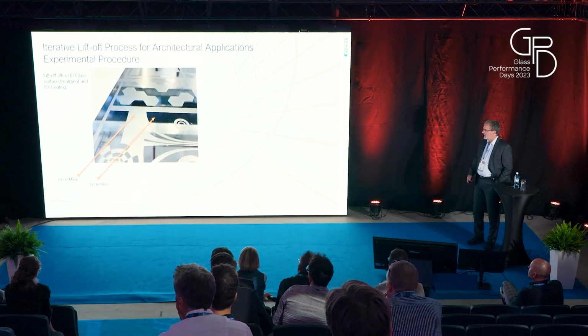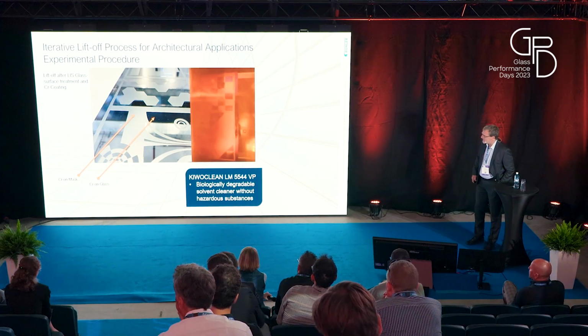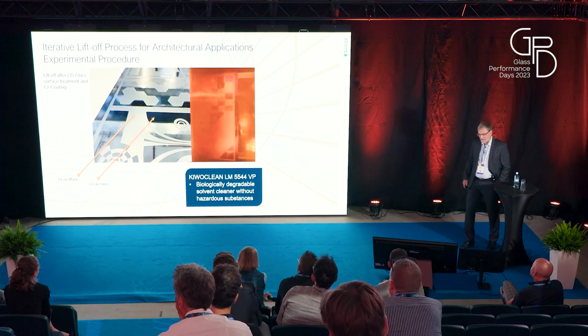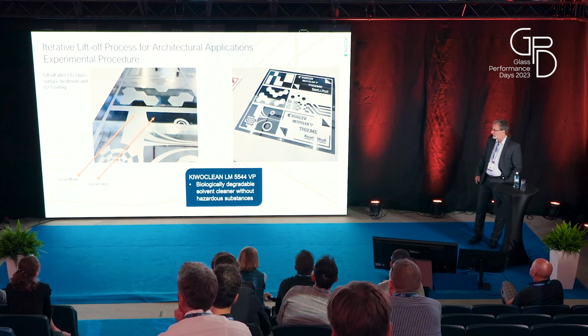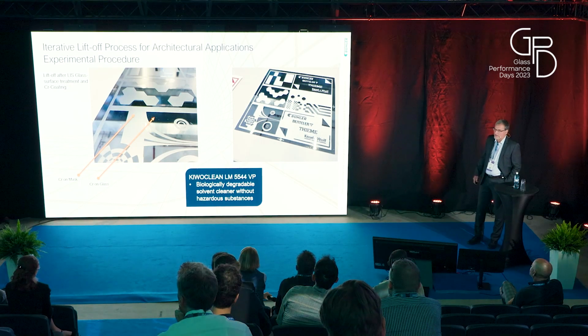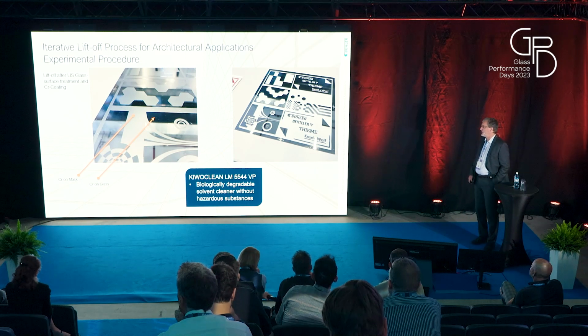So we did this again. So it was the coating, and then again, in the picture, out of the washing machine, it was actually a movie, and I didn't want to run a movie here because sometimes it's really problematic. And then you see in the next picture the result. And so this is actually what we want to achieve. So the linear ion source really helped here a lot to activate and clean the glass surface, and the chrome layer got stuck to the substrate very, very well.